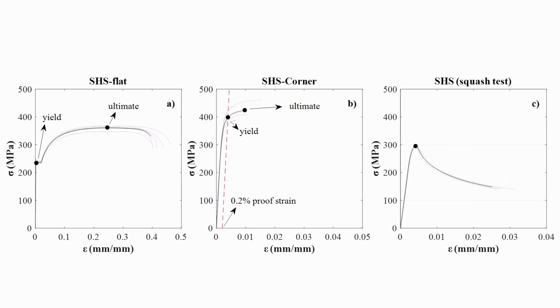Then these are the properties for the steel tubes. We did coupon tests. Because of the cold working of these square sections, residual stresses tend to develop in the corners, so that increases the yield strength. So we did tensile coupon tests from the flat sides of the tube and from the corner sides, and these are the results. And then we did some squash tests, which give a more representative value of the cross-sectional capacity. And we took the yield strength to be that, which was about 295 megapascals.